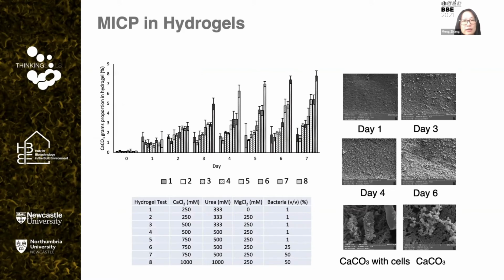Jamie also conducted some investigation on MICP in hydrogels. He investigated the effects of changing reactant composition on calcium carbonate quantity and morphology. As you can see in the figures and the table on these slides, there are many conditions he studied, and there is lots of information that needs to be unpacked from this figure. But the key finding from this set of experiments is that not all the optimized conditions we investigated in the sand column are applicable for the hydrogels.